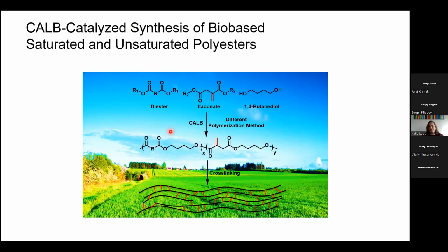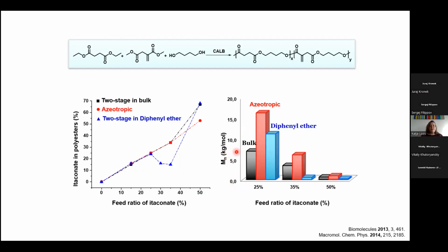If we do it with our enzymatic polymerization, we do it at lower temperatures. We have this free double bond, and we cross-link it later if we want. And this is, for instance, also interesting for 3D printing approaches. It's a bio-based polymer, it's a green synthesis route, and you can later cross-link on demand, which you can't before if you have a classical melt polycondensation.